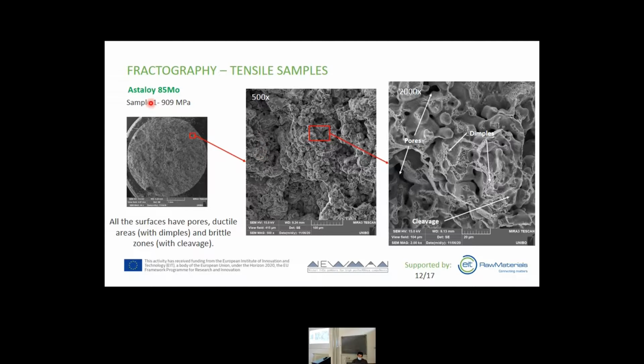For the Astalloy 85MO, all the samples show a lot of pores, which are characteristic of these materials, and they are the reason for the very low elongation of the samples during the tensile test. And then we have ductile areas with dimples and brittle zones with cleavage fracture mode.